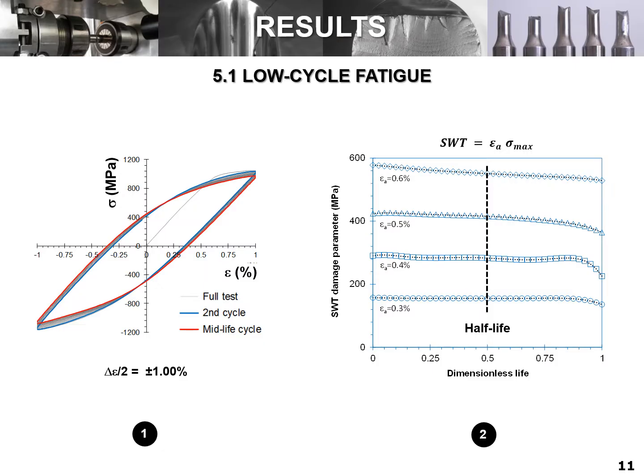The typical cyclic stress-strain response observed in the low-cycle fatigue tests is presented in Figure 1. Regardless of the strain amplitude, this alloy is characterized by a slight strain softening behavior. However, as shown in Figure 2, the SWT parameter is very stable throughout the entire lifetime. Based on this fact, the fatigue damage law representative for this material was created from the half-life cycles.